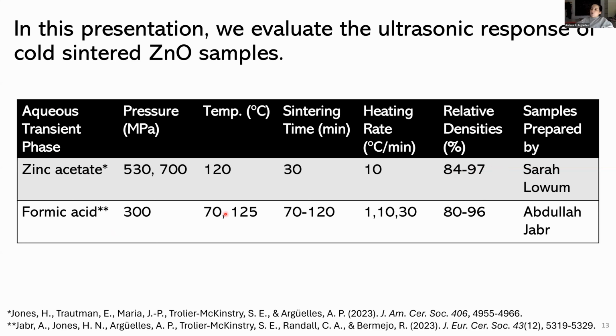97%. In order to obtain that range in relative densities, we needed to change things like the pressure, the temperature, and the sintering time. And then the final thing that we played a little bit around with, because of what ultrasound enabled us to characterize, was the heating rate.